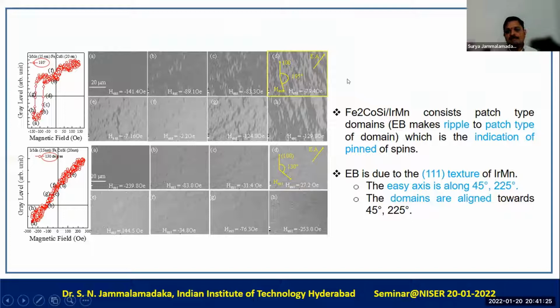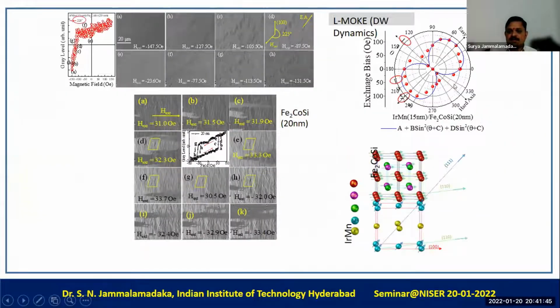Another conclusion that we made is that exchange bias makes the ripple to patch type of domains. Essentially, due to the interfacial pinning, we have the patch kind of domains. The easy axis is along 45 degrees, and this 45 degrees angle is confirmed by plotting the graph between the polar angle and the exchange bias values. We do see the uniaxial anisotropy along the 45 degrees angle.